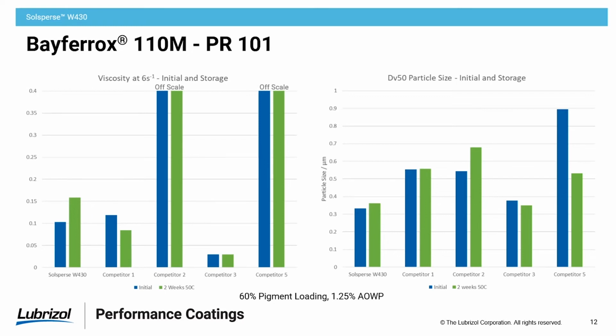In this case, we're comparing for the same systems, the viscosity at room temperature and aged, as well as the particle size, the DV50 particle size, as made and when challenged. And in all cases here on the far left, we have Solsperse W430 compared to a variety of industrially significant competitors. All of these are polymeric dispersants. And so you can see some indications where the comparative dispersants did not perform as well as the W430, because we see either gelling or massive viscosity increase. In some cases, we have viscosity performance which is better. In many cases, the W430 is outperforming the industry standards.